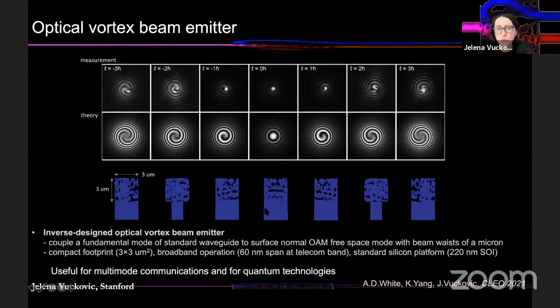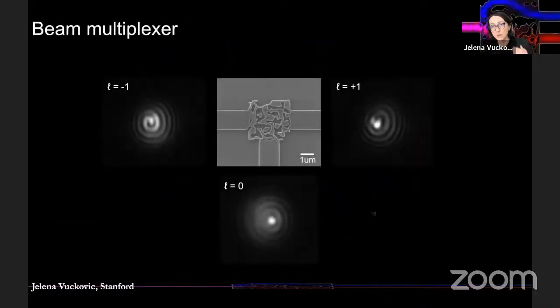And we showed that we could actually do this efficiently, and we could do it also in a broad wavelength range by using these compact elements, 3 by 3 micrometers. So this is something that you could use instead of a phase plate to generate a particular vortex beam at the output. And here you can see how the output beam profile matches theoretical prediction for all of these different designed elements that would convert the guided mode from a silicon waveguide to a free space vortex beam at the output. And maybe most interestingly, you can get another layer of complexity, where instead of just conversion to a particular vortex beam, you can multiplex different vortex beams.